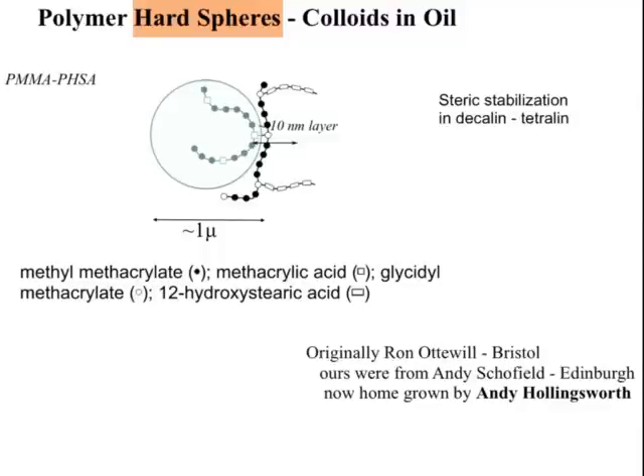These are PMMA, that's plexiglass spheres over here. They're coated because of van der Waals attraction. They'll stick to one another unless you put a little polymer coating on them. So the thickness of this polymer coating is 10 nanometers and the size of the particles is 1 micron. This is like a 1% effect on the size of the particle. Aside from that, there are no interactions between them. This should be a good system for studying this hard sphere transition. And the idea is, as you go to high density, you should crystallize just from the fact that they don't interpenetrate.